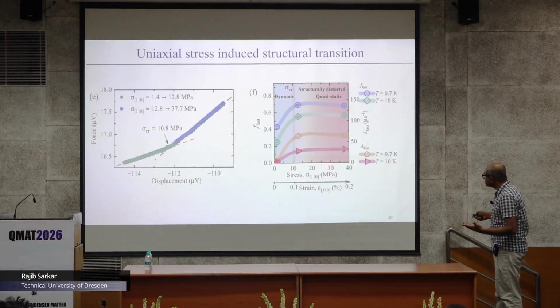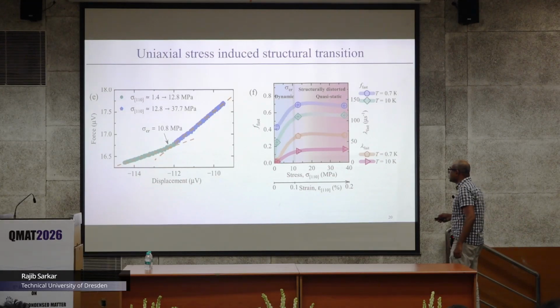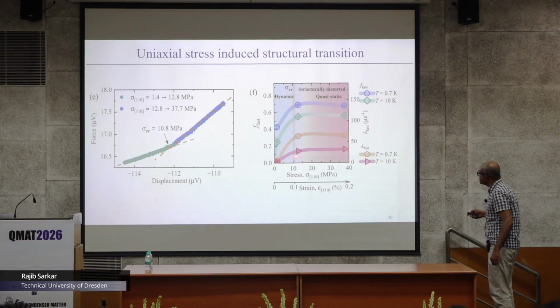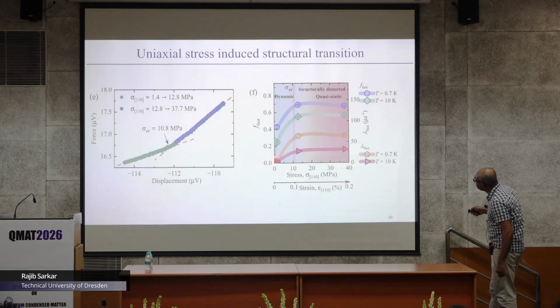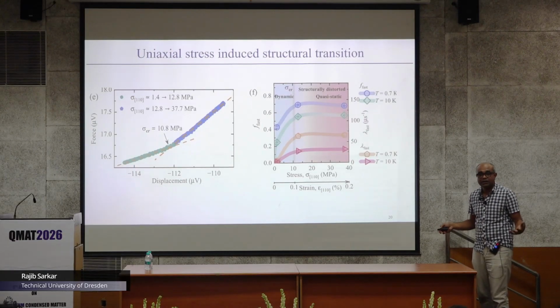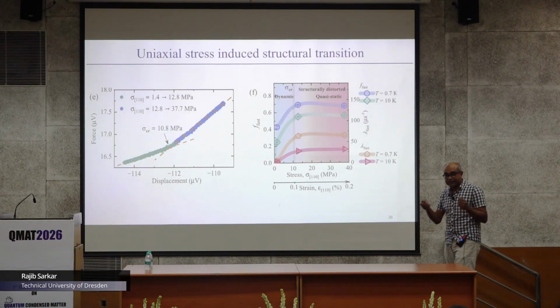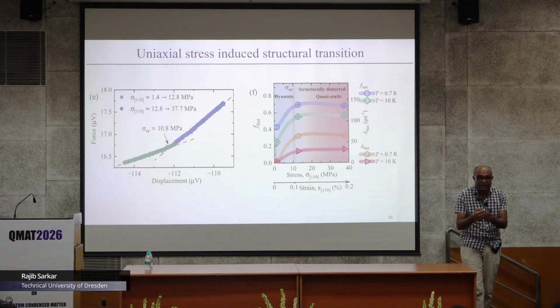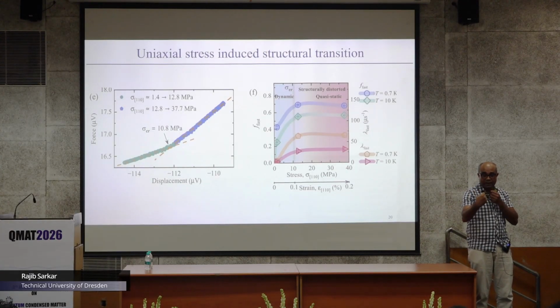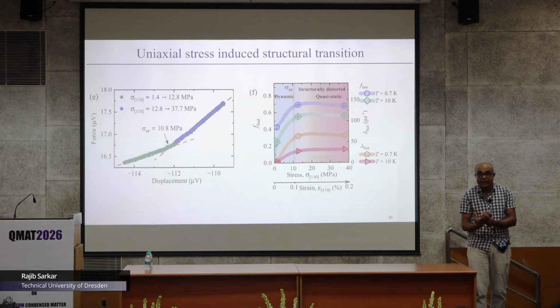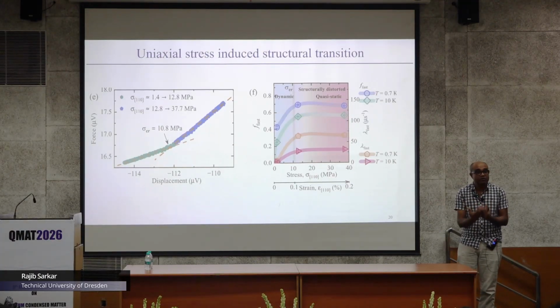So as a function of strain or as a function of pressure, we can make a small plot like that, which is basically lambda first. You see, the 0.7 Kelvin is yellow, and red is for 10 Kelvin, which is the lambda first. These change as you go above 10-point-some megapascal pressure. That tells you that as I apply this uniaxial 110 pressure, I am modifying my system not only crystallographically but also from the correlation point of view.